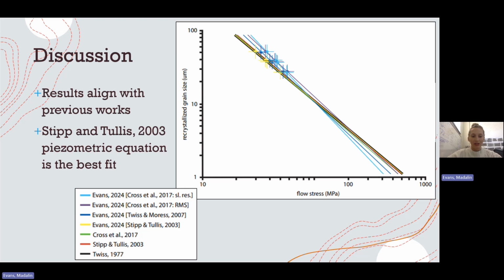The results that were from this experiment specifically are in yellow, darker blue, purple, and light blue, and they have this margin of error over here. So if you can kind of see, there is an increase in paleostress per sample, and that may be due to this 3D approach by Cross and Hall. And again, he is in the light blue and purple, and that is actually the furthest away from this theoretical piezometer here. And that may be because this 3D approach is able to recognize more of these smaller grains and adding them to the data set, therefore increasing stress, whereas the 2D method is not as effective in identifying these smaller grains.